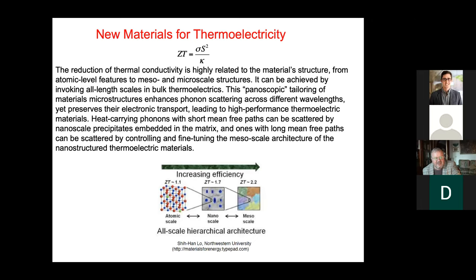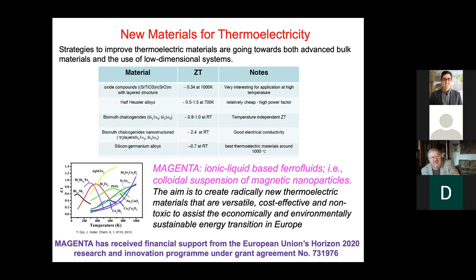This panoscopic tailoring of materials' microstructures enhances phonon scattering across different wavelengths, yet preserves their electronic transport, leading to high-performance thermoelectric materials. Heat-carrying phonons with short mean-free paths can be scattered by nanoscale precipitates embedded in the matrix, and ones with long mean-free paths can be scattered by controlling and fine-tuning the mesoscale architecture of the nanostructured thermoelectric materials. So in new materials for thermoelectricity, you can see which values already are achieved. In oxide compounds, half-Heusler alloys, bismuth chalcogenides nanostructured, and you see that the numbers which I told are